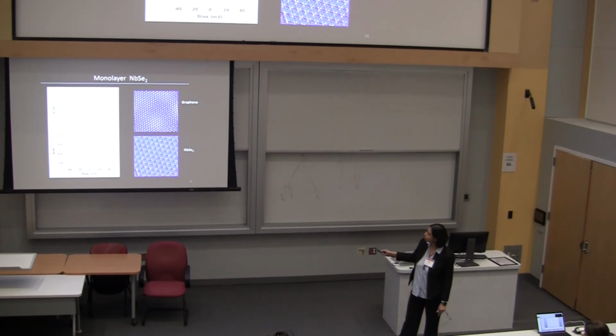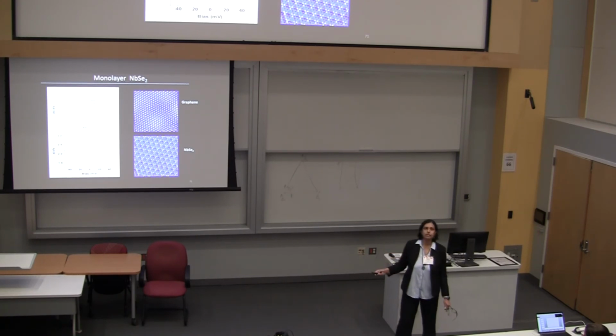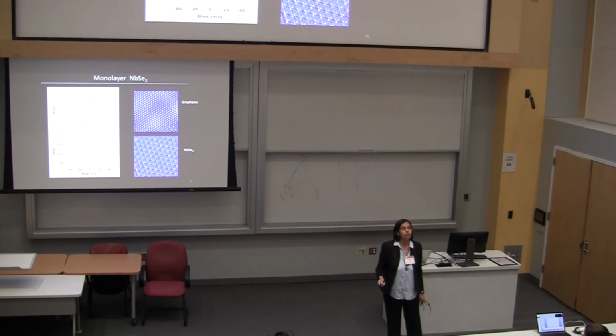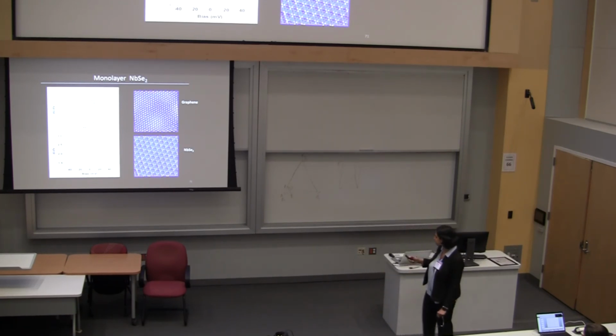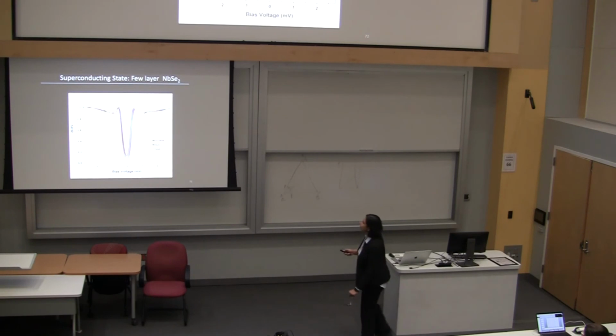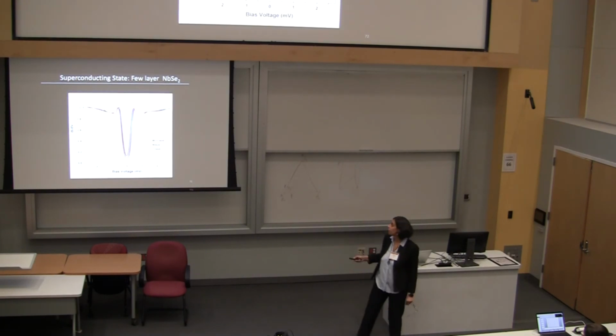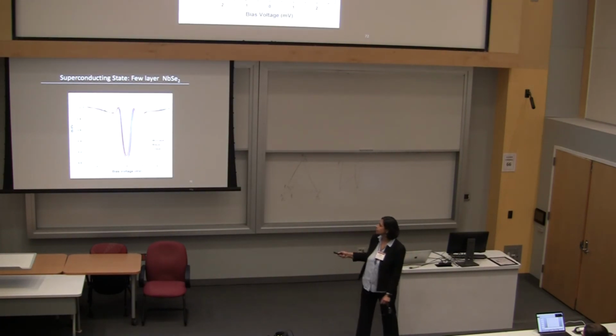If you zoom in right here, close to the Fermi energy, you can actually see the little kink right here. You see this gap? This is the charge density wave gap of niobium diselenide. It's about 5 millivolts, or something like that, between 5 and 7 millivolts. Now, if you zoom in some more, look at this energy scale. It's much smaller. You can see the superconducting gap.